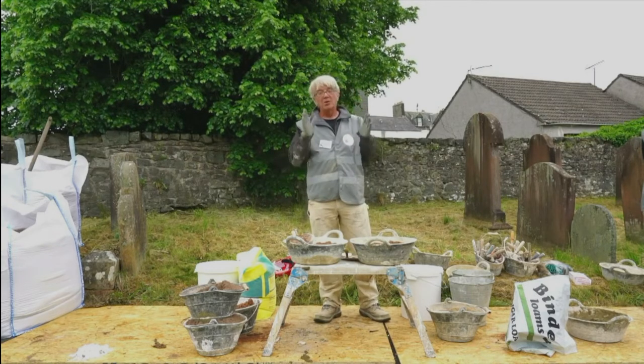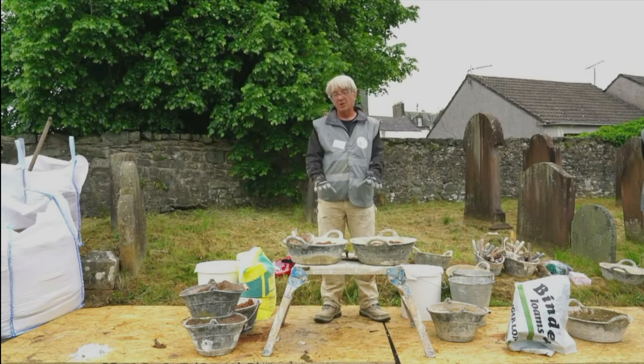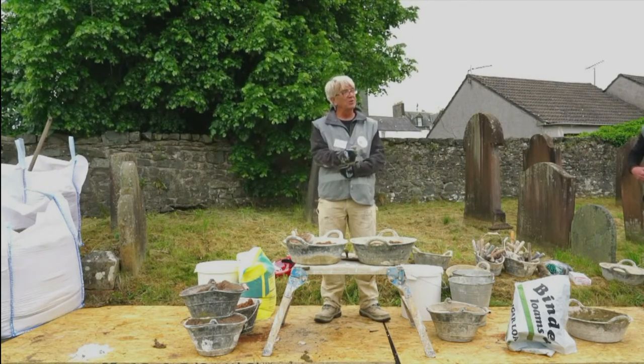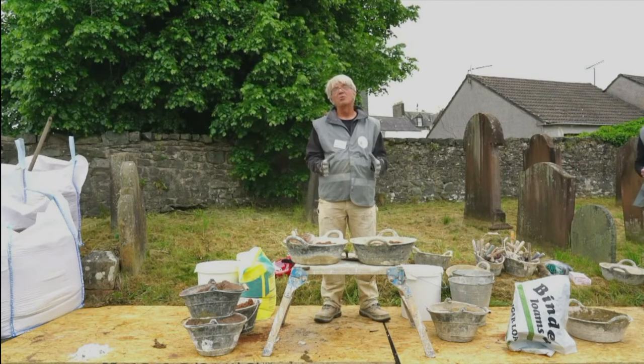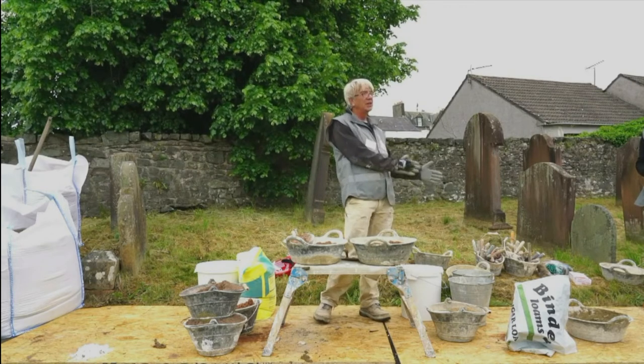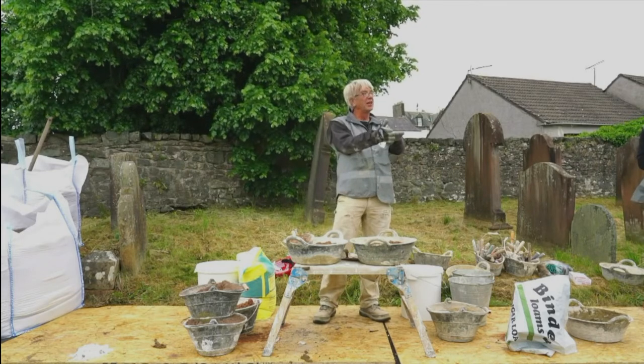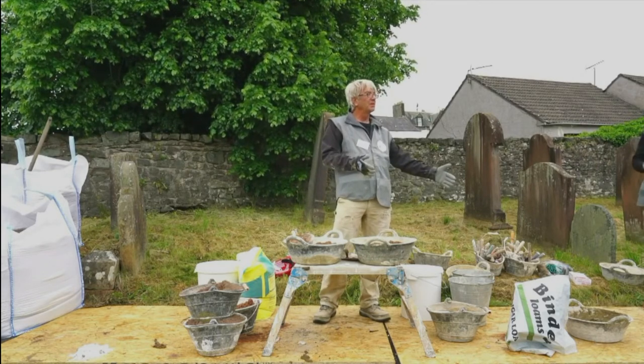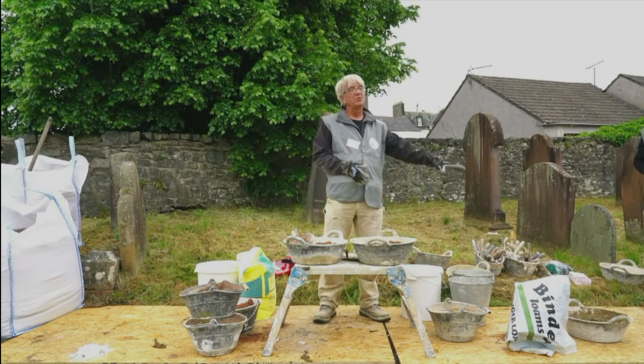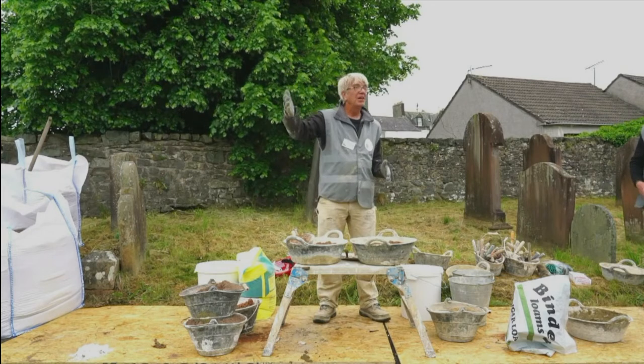Anyway, for most of history, they talk about slaking the lime by giving it water, a quicklime, and this is how they made lime putty as well. You would add just sufficient water to the lump lime so that it slakes properly. Then you would dilute it sufficiently that you could pass it through a screen. When you get these multiple lime tanks, there's a grill in between to remove unslaked lime. It goes into the bottom chamber. The sand might then be mixed with it, and that's a hot mix. Or it might be left to mature, but in that case, usually, for use, as I've talked about.